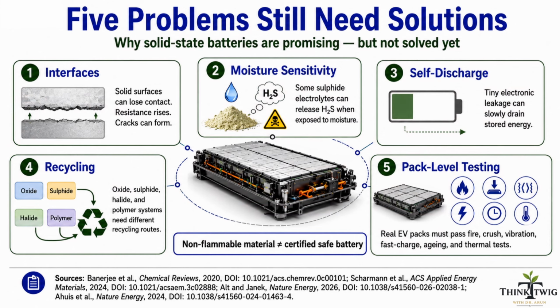So, what is still unsolved? The first is interfaces. Liquid fills gaps, solids do not. So, during cycling, solid surfaces can lose contact, resistance can increase, cracks can appear, and performance falls. The second is moisture. Some sulfide electrolytes conduct ions very well, but moisture can make them release toxic hydrogen sulfide gas. That means dry rooms, gas monitoring, careful handling. The third is self discharge. Even a tiny electronic leakage current can slowly reduce stored charge. Fourth is recycling. Oxides are different from sulfides, which are different from halides, and polymers are different again. So one recycling method may not work for all of them.